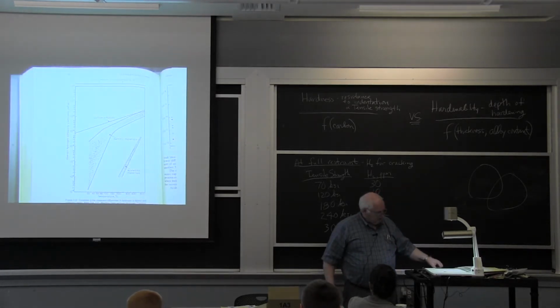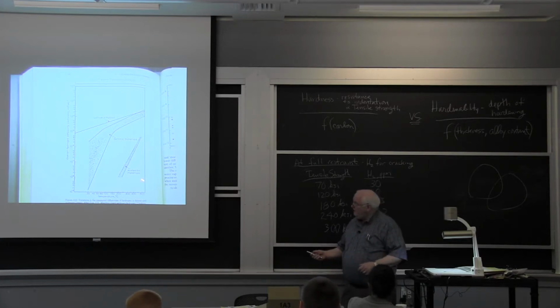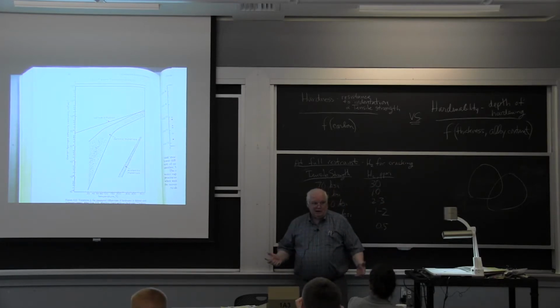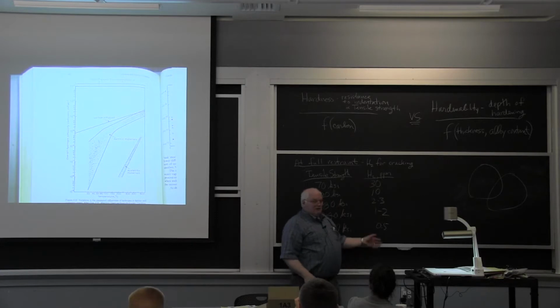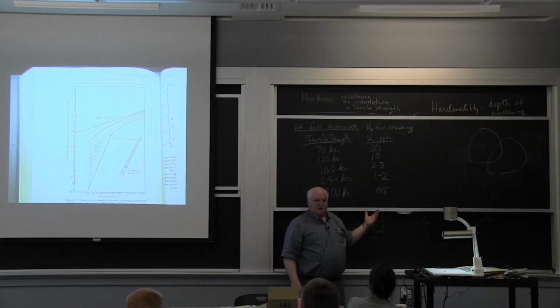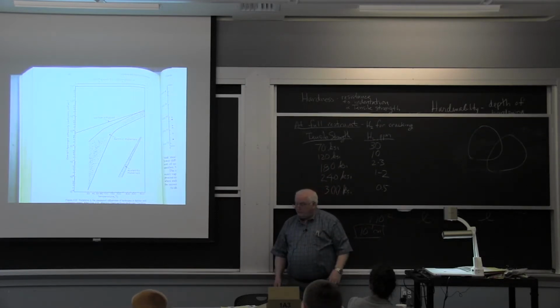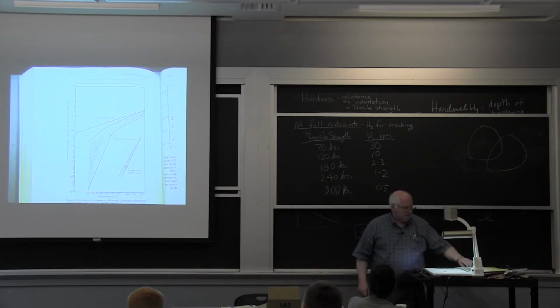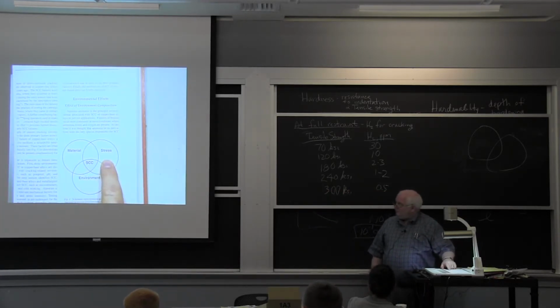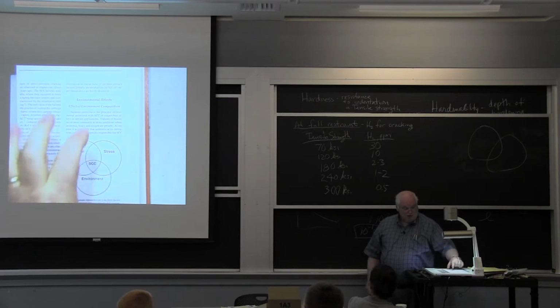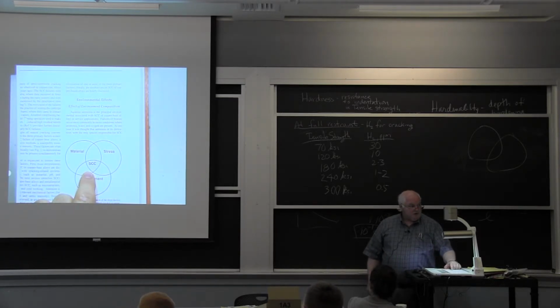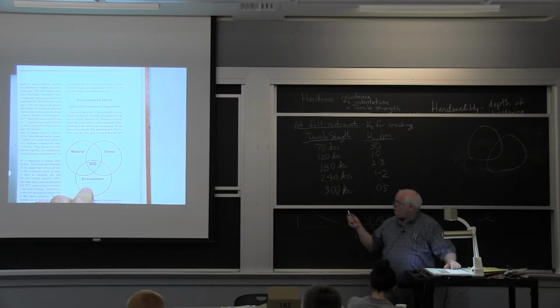But the point of this plot of the diffusivity is you can calculate how long you've got to keep something hot to get down to these types of levels depending on your strength. And the higher the strength, the bigger the residual stress circle, the bigger the region of stress corrosion cracking or hydrogen cracking. Your environment is how much hydrogen I put in there to begin with from the welding operation. It has 30 parts per million.